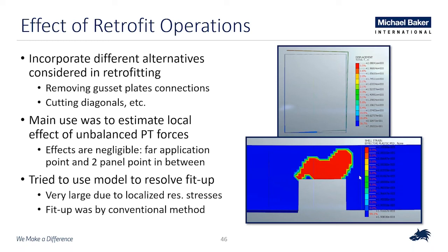The problem that we had in here is that if you attempt to do this by the use of localized application of localized forces in this local model, because you have that region on the bottom flange that was pretty much cold work, in order to square the box, what you're doing in the model is basically reworking that region. You are again applying forces to overcome those residual stresses and then re-deform that region. So you end up with pretty high demands for that squaring to be accomplished.